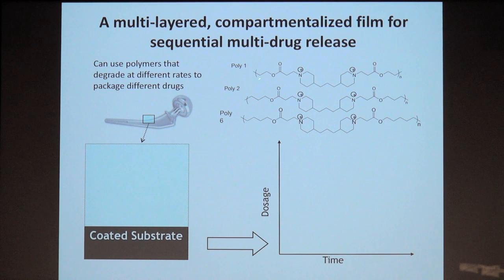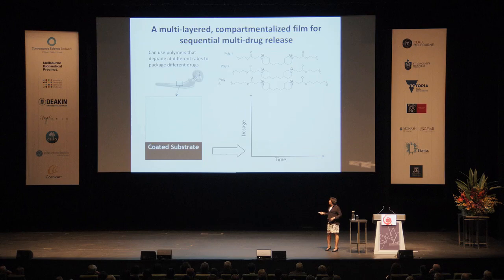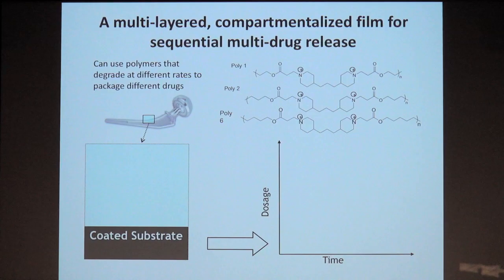Here we're making this little region, which is essentially a carbon-hydrogen bond. We're going to increase the number of these CH2 linkages and make this longer and longer. That makes it more and more water-hating. That means that it takes longer and longer to degrade. I can actually tame that by layering a drug with this degradable positively charged molecule.